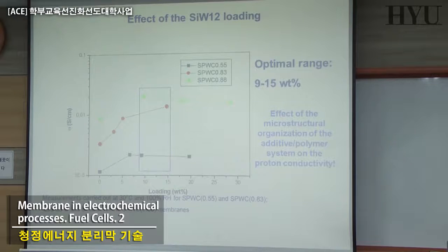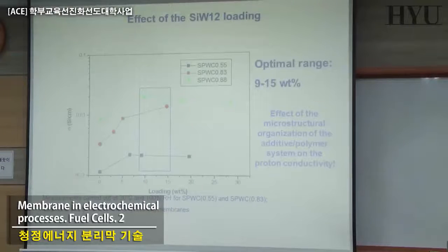However, for what has been done until now, you don't know. It's interesting results, interesting publication, but Nafion is still there. We are still not able to replace it, and if you increase the presence of the superacid by more than 20-30%, you start to lose mechanical properties or you have leakage. So you have to find something different, a different kind of superacid or a different way to immobilize it in the membranes. So that is basically it.